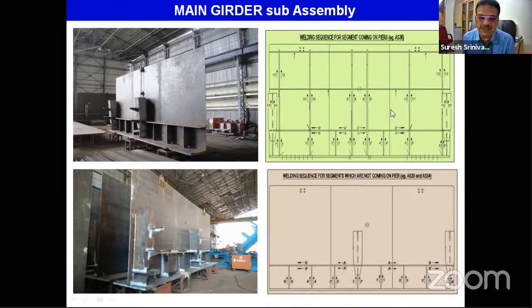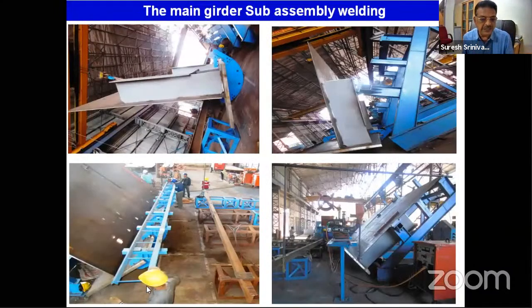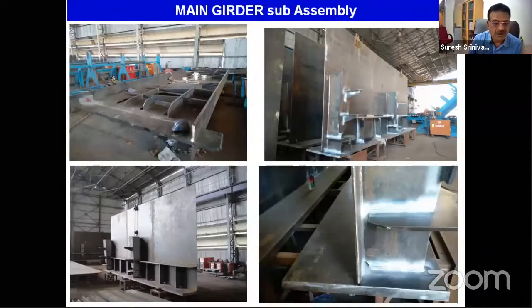Again, we applied a weld sequence such that the squareness of this plate does not have a bend or camber, so that welding with the deck plate will not create a problem for us. So these are the welding sequences followed. And you can see the various snapshots of how we welded this main girder using the makeshift fabricated fixtures at site, and again automated or mechanized semi-automatic welding was done here, and then tilting it again, doing the welding after the back gouging, back grinding is done. So this is the tractor which we use for semi-automatic welding. You know this, all this.